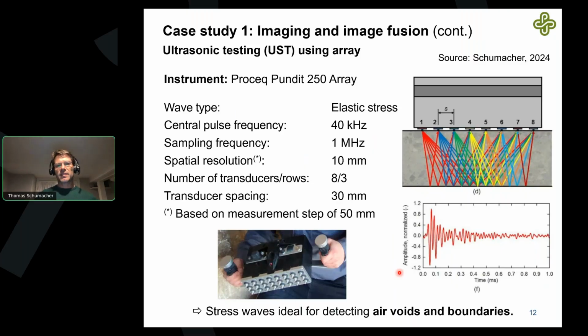The second device we used is this ultrasonic echo array. This is a Pundit, and it has 24 transducers, but it's really 8 channels, 8 rows. So 3 of these always act as one channel. So it's really an 8-channel unit. You can see that now we have all these different combinations. Channel 1 sends a pulse, all the others are receiving that pulse. Then channel 2 sends a pulse, the rest of the channels are receiving. Channel 3 sends a pulse, and so on. So in one location, you basically get 28 measurements. And below, here's an example of one such measurement.